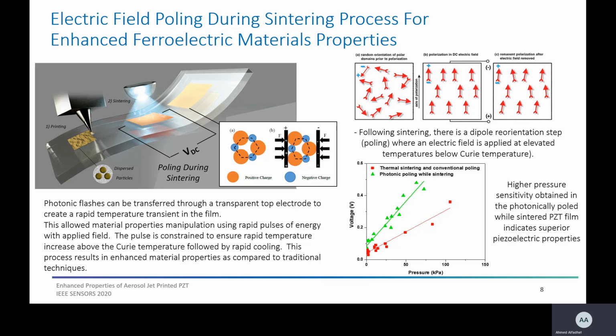The voltage was applied between a top transparent electrode that allows flashlight penetration and the substrate that acts as a bottom electrode. It was observed from the pressure sensitivity test that we obtained higher sensitivity with the photonic sintering and poling process compared to conventional poling as a separate step.